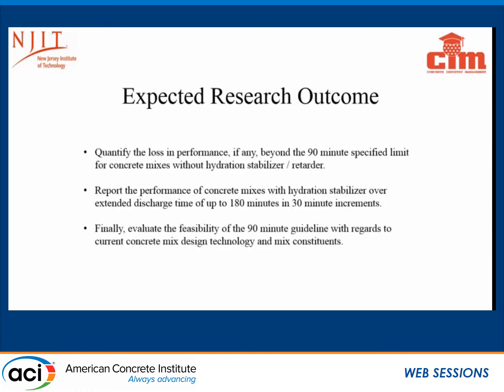So, expected research outcome: pretty much to determine that there's no loss in performance of the mixes when going beyond 90 minutes. One of the things determined to be used is a hydration stabilizer, because it has been proven that hydration stabilizers and retarders help the concrete perform in the intended way when you want to go beyond 90 minutes. Repeat performances of the concrete mix were done over 180 minutes at 30-minute increments, as I alluded to earlier, and then the results were evaluated at the end.